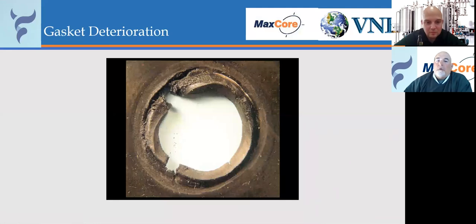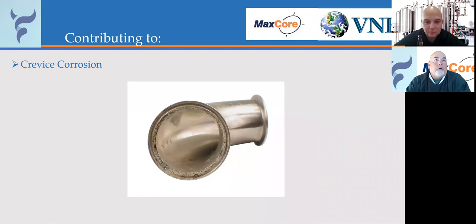But then you're also going to end up with a face on your flange that looks something along those particular lines. So you have these areas that are corroded all around this, and this whole area then becomes anodic. And you've created another anodic site for corrosion to start to take place. And as those metal ions are released, again, you're putting iron into the system, which can relate to rouge further down the system.